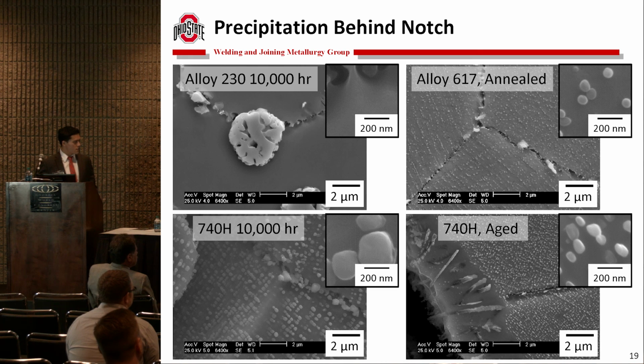The questions that are arising for me, though, have to do with alloy 740H. If you've been following my work or Dan Bicchetti's work, you may know that there are discontinuous precipitation reactions where gamma prime forms perpendicular to a grain boundary, and the coarsening discontinuous gamma prime forms at the expense of the regular gamma prime. And I wish I could say that this crack was formed by that, but I'm not sure I can. And I want to, before I move on, point out that this is a similar surface breaking crack. It's important to note these are surface breaking cracks in the 10,000 hour aged 740H, and they're very clearly